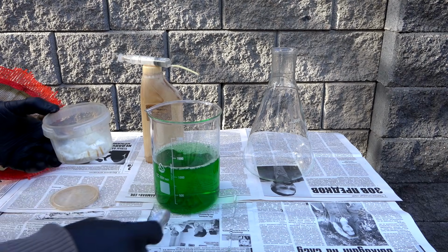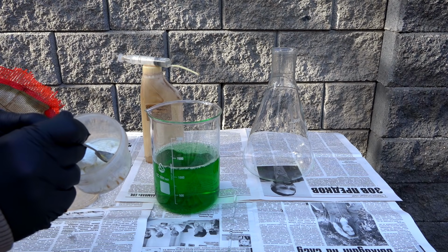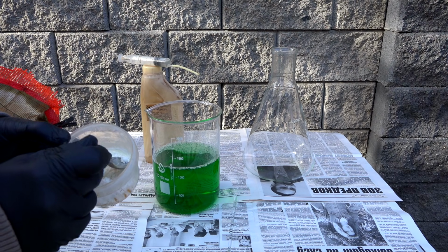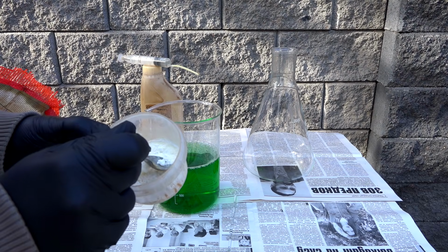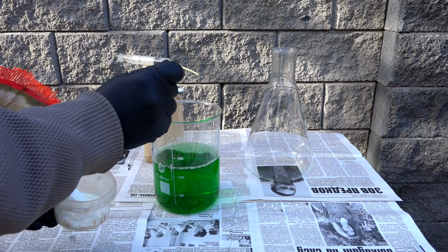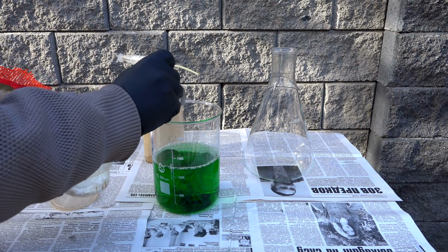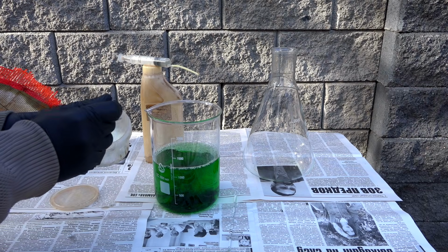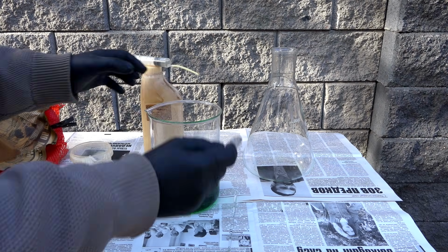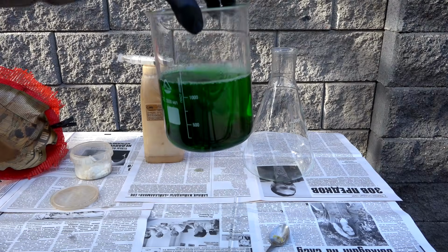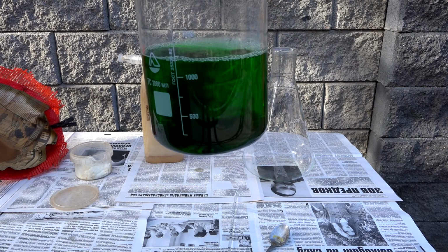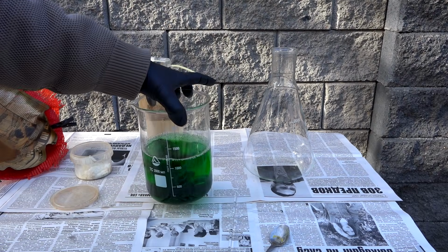For example, sulfide reagents shouldn't be used in the initial step, otherwise, along with the gold, various turbidities and dirt will separate. I first add stannous chloride to the solution, which separates the gold, and since the solution contains nitric acid and sodium chloride, to prevent the gold from redissolving, I add hydrazine hydrate to stabilize the solution.